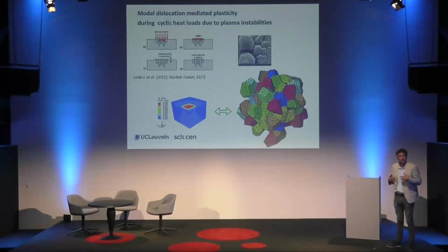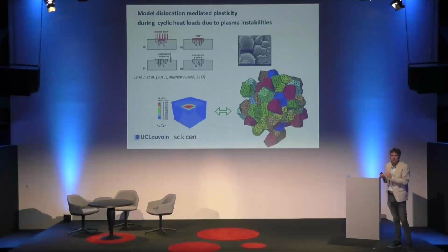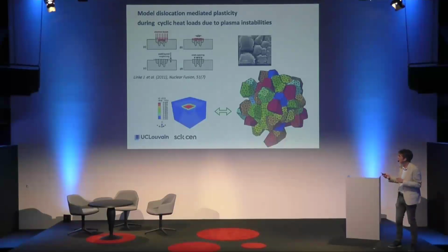We have an expertise in Louvain about the modeling of so-called crystal plasticity, really modeling plasticity at the scale of individual grains, where we know that dislocation glide occurs along different planes in the different grains. The behavior of the grains is very anisotropic, leading to stress concentrators, which are at the origin of damage, of the cracks.